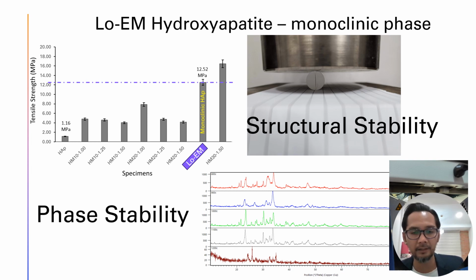So this is the advantage of having the monoclinic phase. You can see that our low M has the highest tensile strength. We used the DTS method, diametrical tensile stress. We have 12.52 megapascal, which is good compared to the HAP control sample sintered at 900 degrees Celsius, where we only achieve 1.1 MPa. I'll say the highest one besides the monoclinic HAP is basically not the HAP phase. We are not able to get the hydroxyapatite phase, so it is of no use.